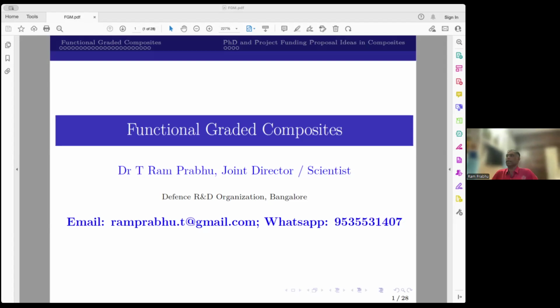Okay, fine. Any composite related papers, it seems all kinds of tests were displayed in the PPT. Is it required that all the tests are necessary for composite materials? The first thing is I don't know whether all the tests are done. If you look carefully at my third slide, as I said there, you have to figure out what the application is and only the relevant test should be done, not at the whims and fancy of doing tensile test, fracture test, and XYZ tests. The minimal requirement is at least hardness, to see what you have made. Sectional hardness, not the surface hardness. If it is a polymer, people generally do the flexural test. But if your particular part application undergoes bending load, then you need the flexural test. Otherwise, it's not required.